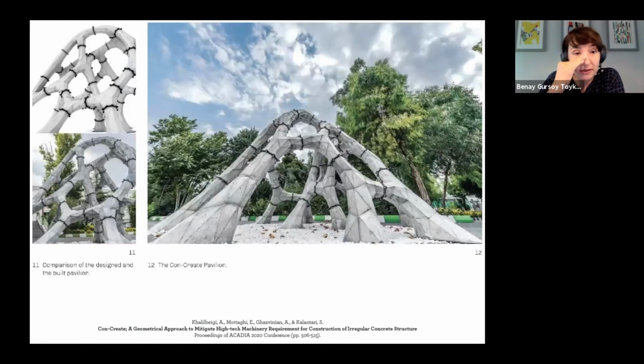A little bit of background: Arman and Ismail are two collaborators in this research. They're from Iran, not from Penn State, and they have previously built a structure called Concreate, using concrete. And as you may know, mycelium-based composites work best under compression, and they are very weak in tensile strength. So the form finding of the concrete structure that they developed was suitable for an exploration also with mycelium, because the structure works under compression. So we worked with them.